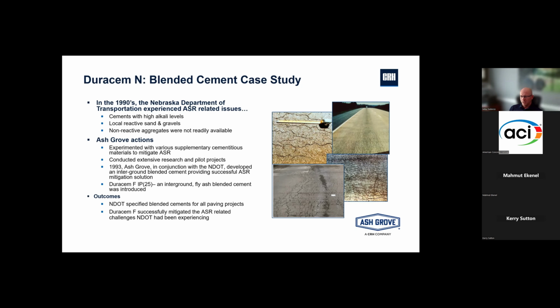Duracem F has been successfully used since 1993, so over 30 years, in that market as an interground blended cement, and it has performed well throughout history. As a result of all of that, NDOT saw the results. They were fabulous for them. It really reduced their issues, and they began to specify blended cements for all paving projects. As a result, Duracem F was a successful commercial launch starting in the 1990s up until today.